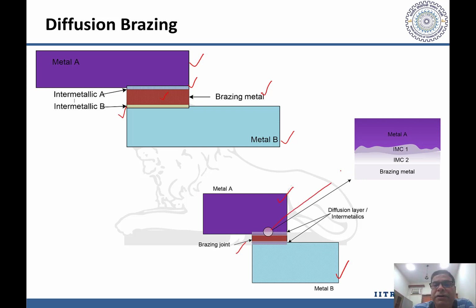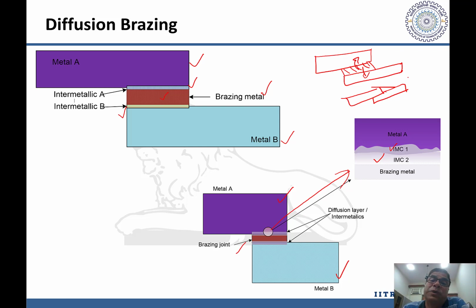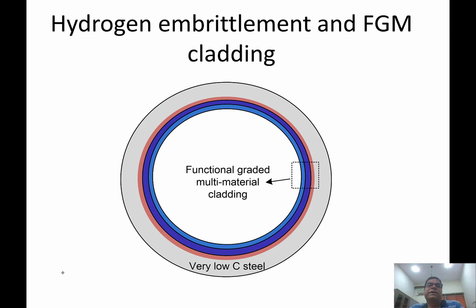If we see the magnified view of this, then we will see a variety of IMCs being formed. It's important that these IMCs are really favorable for good joint strength, as compared to this conventional one, when we use diffusion brazing. So in the beginning, definitely we have to apply the brazing material, but during the course of the diffusion brazing process, this entire brazing material gets diffused out. This leads to a joint strength which is almost as good as the strength of the weaker base metal.